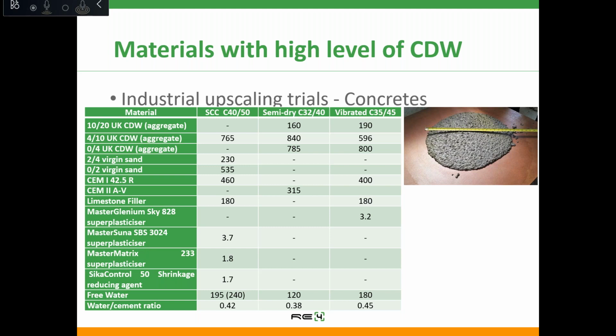These mixes contain CDW aggregates, cement, and limestone fillers. For the structural elements we used three mixes: one self-compacting concrete, another a semi-dry concrete, and a vibrated concrete. The vibrated concrete was to be used in the stairs manufacturing.